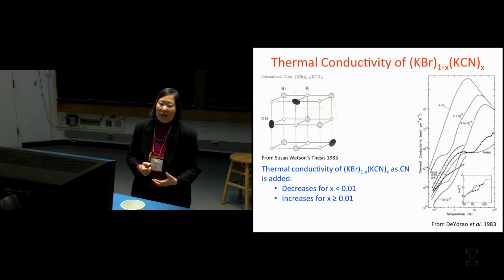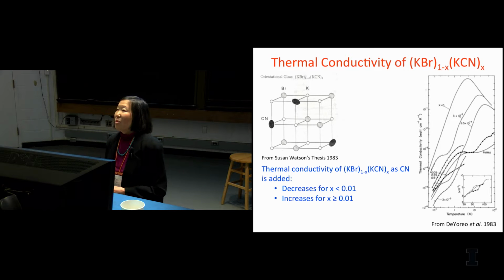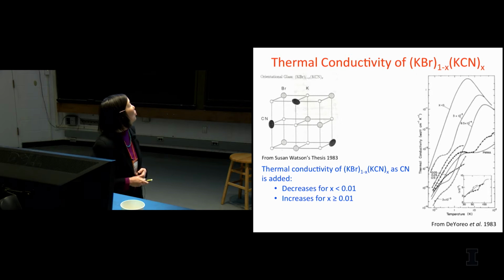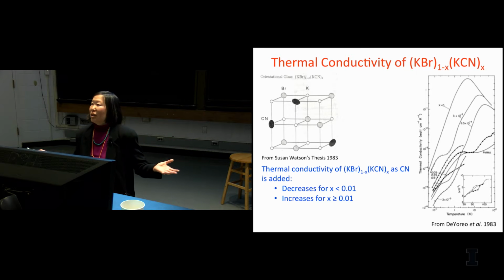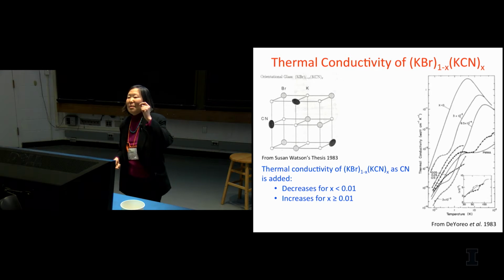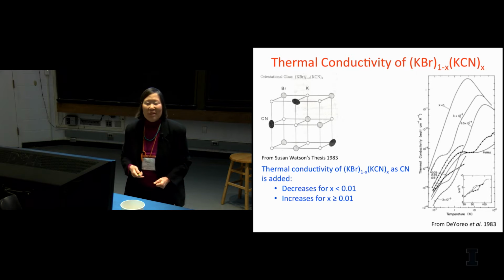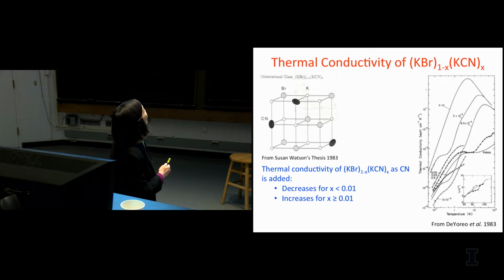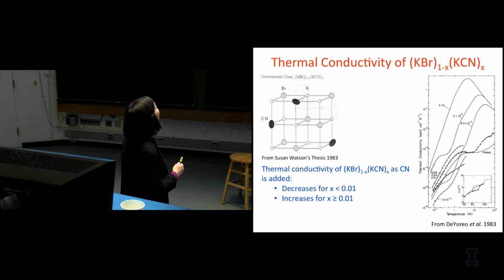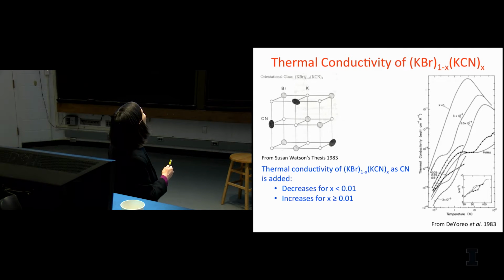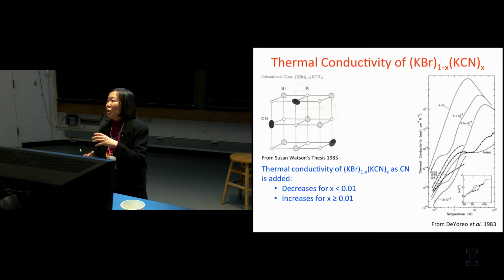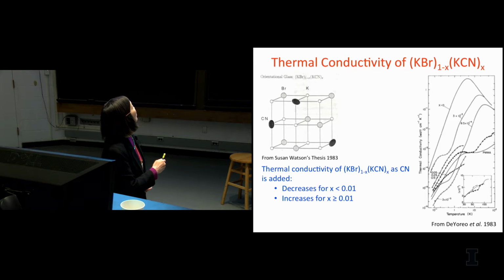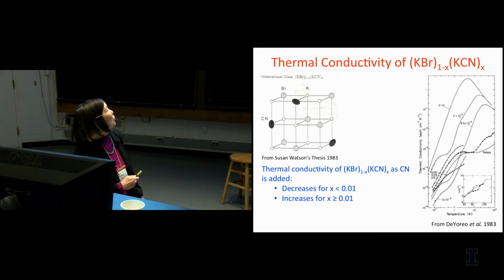And when I started working on glasses, one of the things that caught my eye was some work coming out of Bobby Pohl's group at Cornell. It's true you don't usually know what the two-level systems are, but sometimes you can deliberately put in something and say, well, that's my two-level system, and this is the case of KBr-KCN. Potassium bromide has the structure of sodium chloride, and you can take out the bromines and put in these cyanide molecules, which are big, fat, football-like strain quadrupoles, and they can reorient in 8 different orientations, and that then is your two-level system.